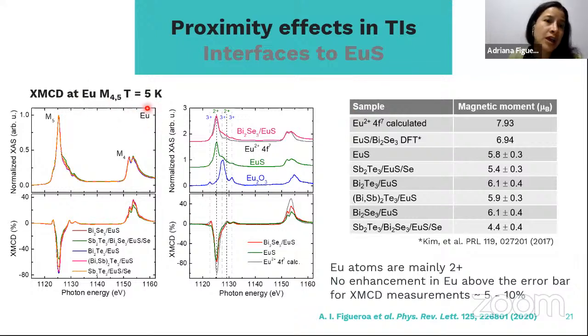The first results that I'm showing here are the ones at the europium energies. We observed that the europium atoms in all these stacks are mainly 2+. I mean, the valence is 2+, which is the one for ferromagnetic europium. And we observed that there is no enhancement of the europium, by application of the magneto-optical sum rules to the XMCD signals that we observed on the europium atoms.